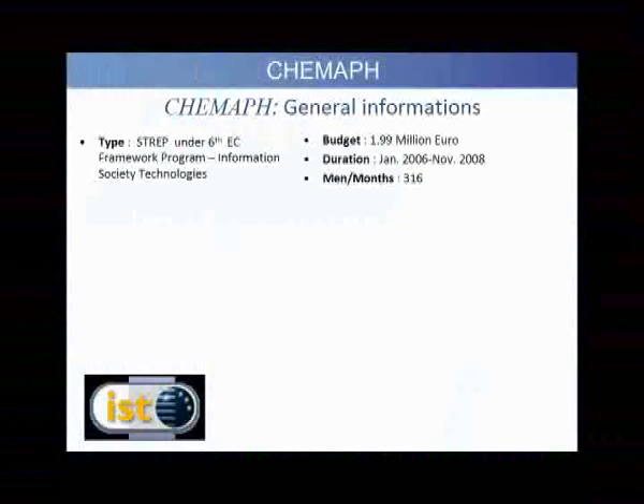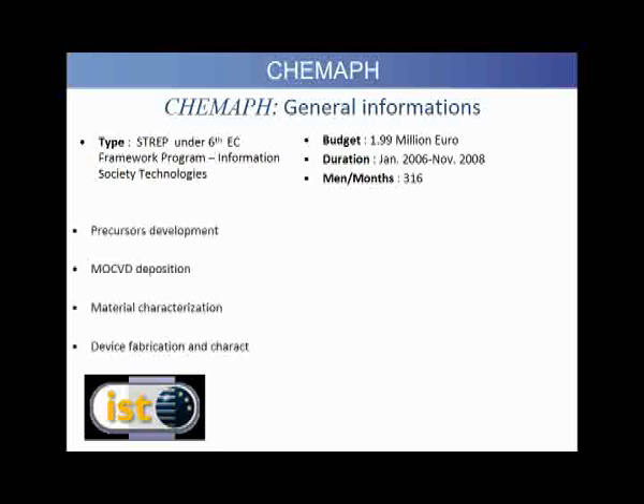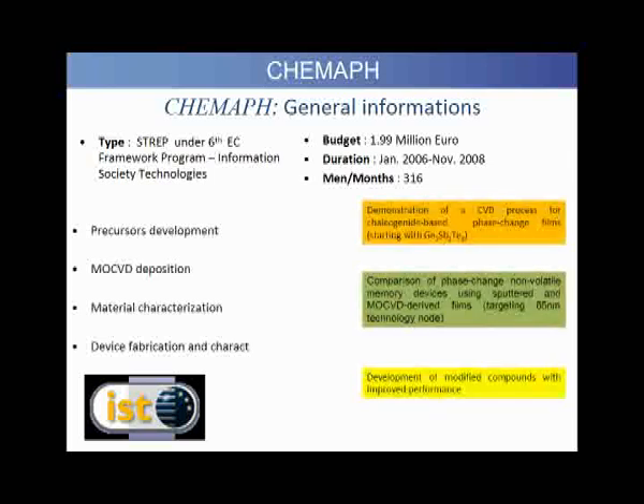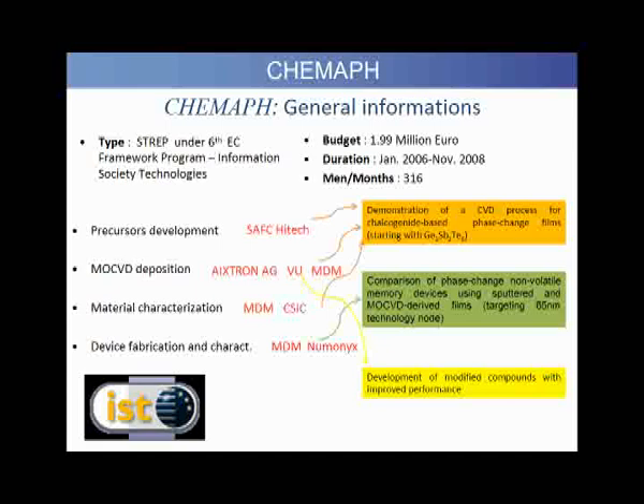The main achievements of the CHEMAPH project include the demonstration of CVD process for chalcogenide-based thin films, the evaluation of phase change memory demonstrators including MOCVD chalcogenide materials, and the development of modified compounds to improve the performances of the cells. The role of our MOCVD system within the CHEMAPH project was to study the growth of germanium, antimony, tellurium binary and ternary alloys, aiming to obtain phase change materials comparable to what is obtained with sputtering and trying to improve the deposition conformality, that means uniformity, within structured substrates.